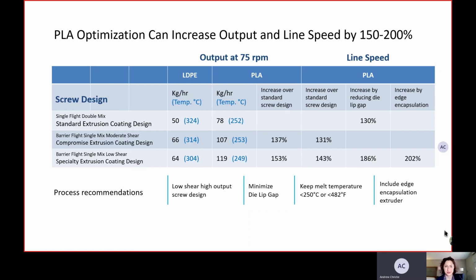So if you have a low shear screw, you get increased output from your extruder, 119 kilograms per hour, and a lower melt temperature, 249. That's an increase of 153% in output. In line speed, that's a 143% increase. If you do that and reduce the die lip gap, you can get 186% of your line speed. And if you have edge encapsulation as well to help stabilize that curtain, you can get a 200% line speed increase.